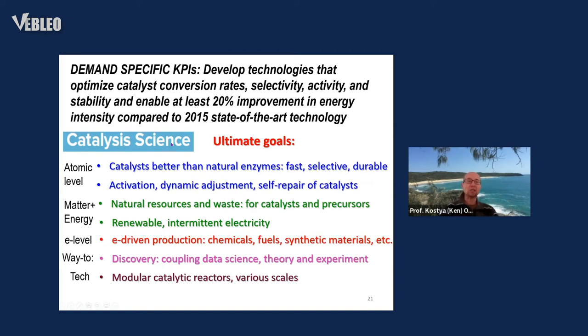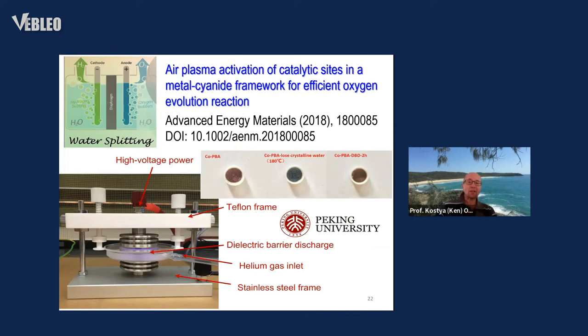So to address these facts, we develop plasma systems, plasma processes that can enable such features, such high-performing catalysts and energy-efficient and effective processes. Let us start from the high-performance catalyst that is targeted for one of the most in-demand processes, electrocatalytic water splitting using water electrolysis, for which catalysts are needed to sustain both half reactions of production of hydrogen on the cathode and oxygen on the anode. And we particularly address the production of the catalyst for the oxygen evolution reaction on the anode, which is widely considered as one of the most difficult and challenging.